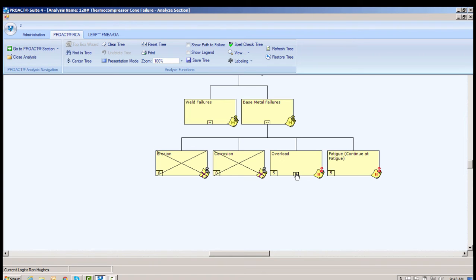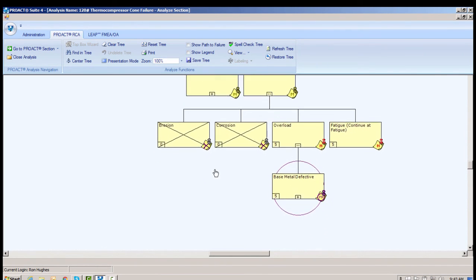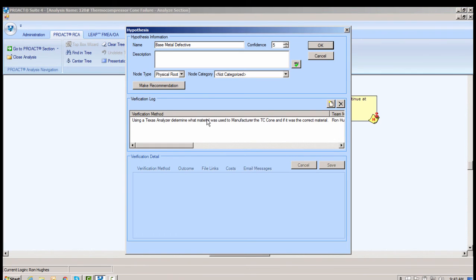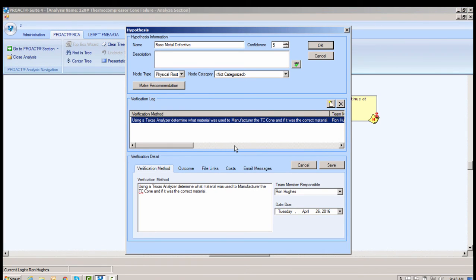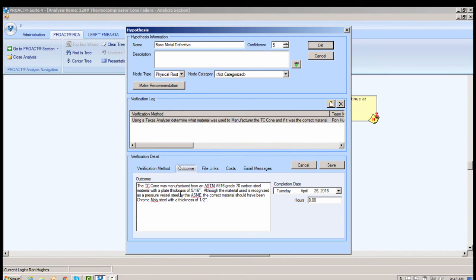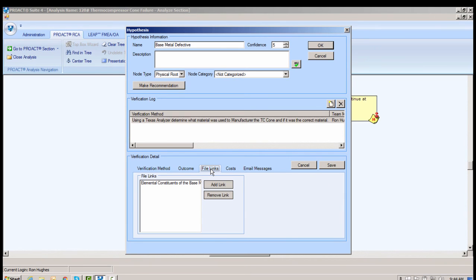Alright. Overload. Base metal defect. Okay. So we use a Texas Instruments analyzer because we want to verify what the base metal actually is. And we're going to look for the elemental constituents of the base material. And we find that the TC cone is manufactured from ASTM A516 grade 70 material. Now this is a pressure vessel material. This is a good material, but it's not the right material for the service that we're seeing. For the service that we're seeing, we need something with more chrome and more molybdenum to give it higher strength at a higher temperature.